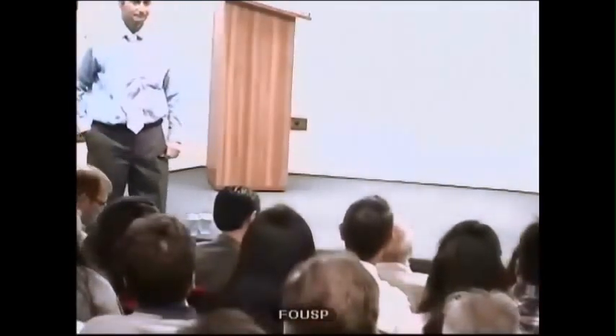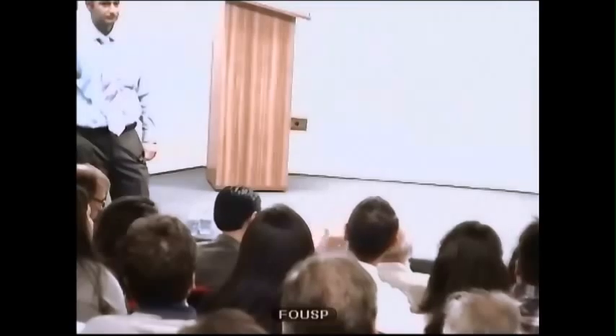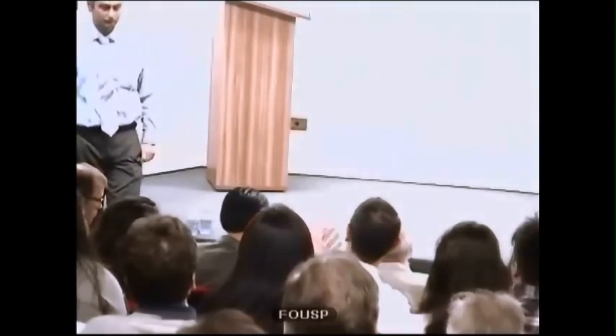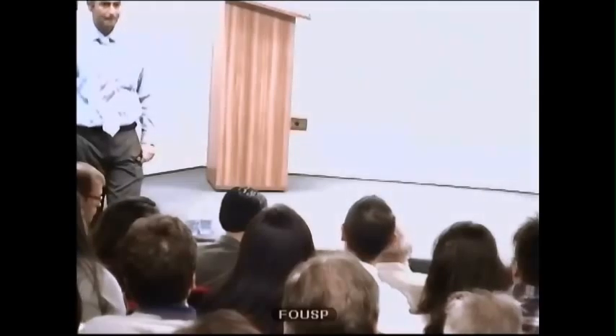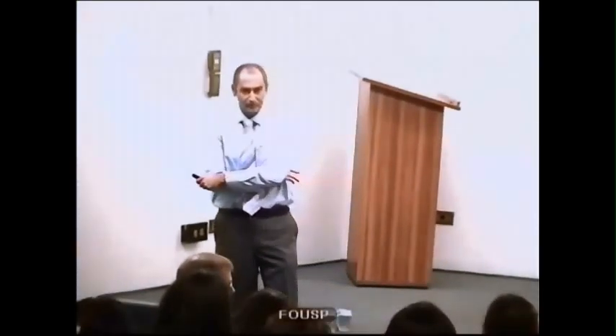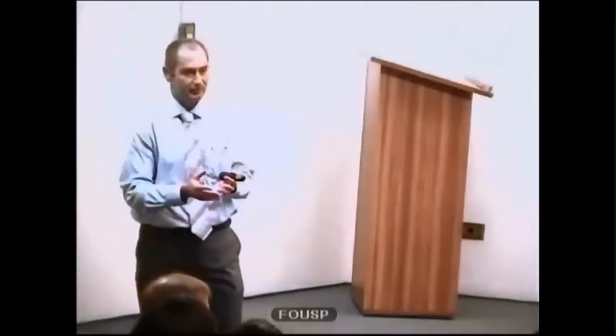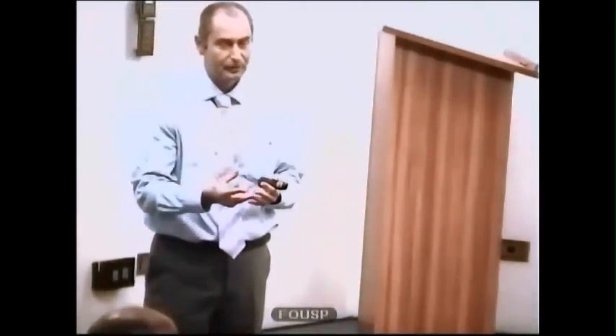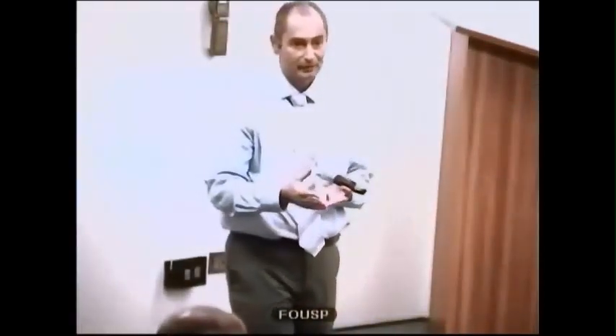Nick, thank you for the presentation. One of the graphs you showed indicated that irregular fillers provide a little higher elastic modulus compared to spherical fillers. What's your hypothesis for that? Because in theory, you shouldn't expect any movement of the filler in the matrix once it's cured. The differences, first of all, were only with nano indentation, which is a more local phenomenon, rather than with the universal testing machine that looks at the whole of the material in bulk. So part of the differences could be because that effect is very localized.